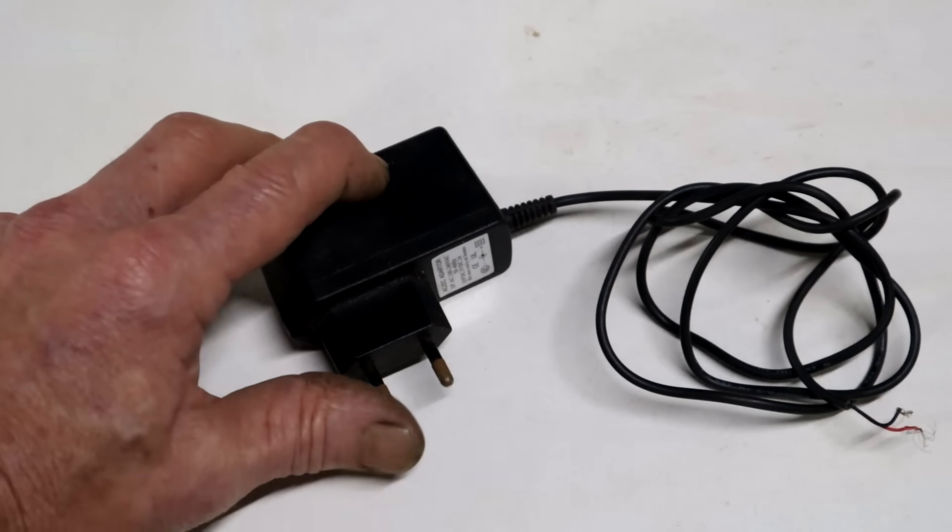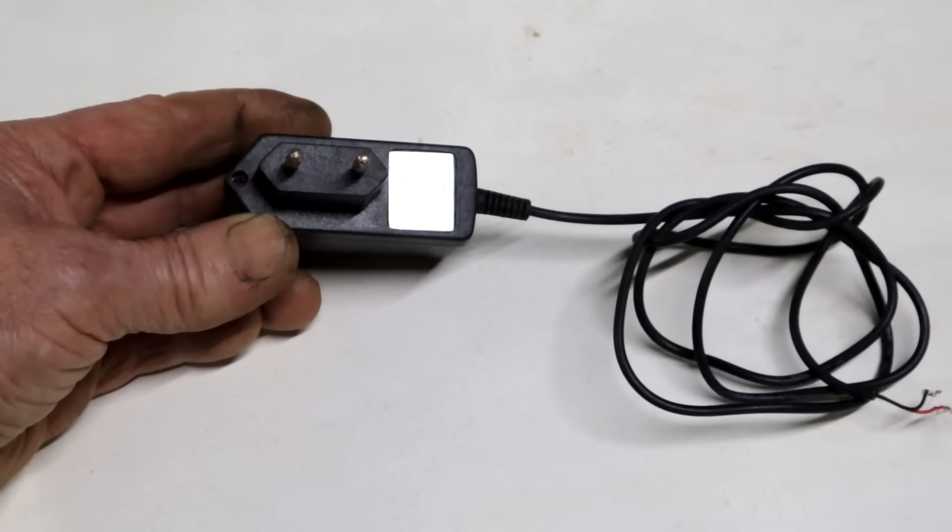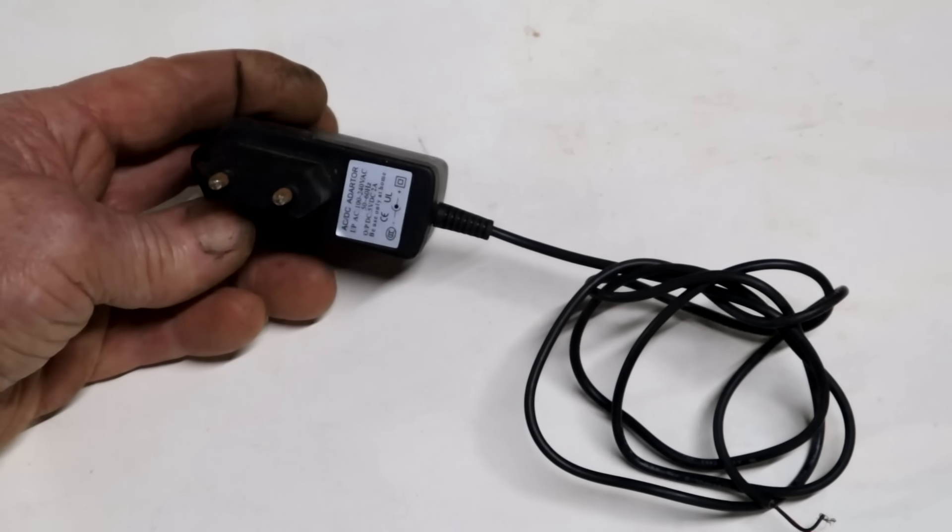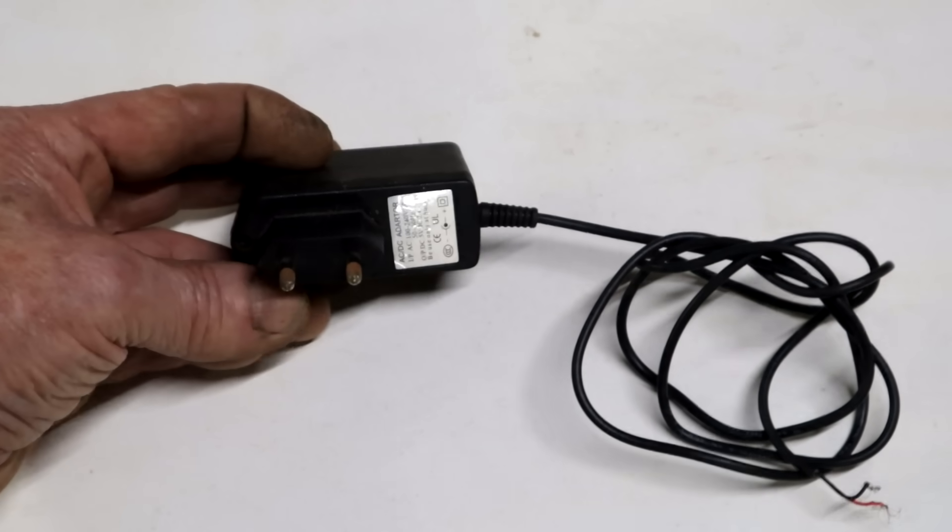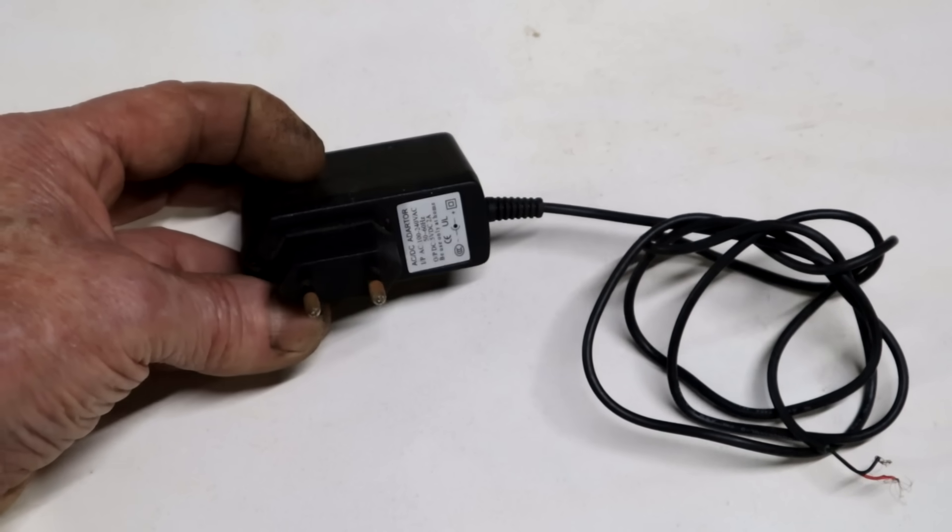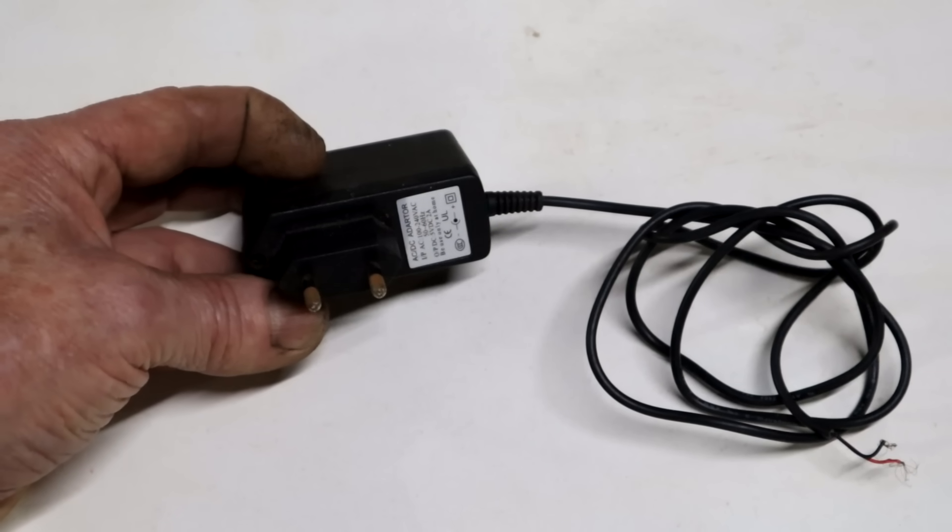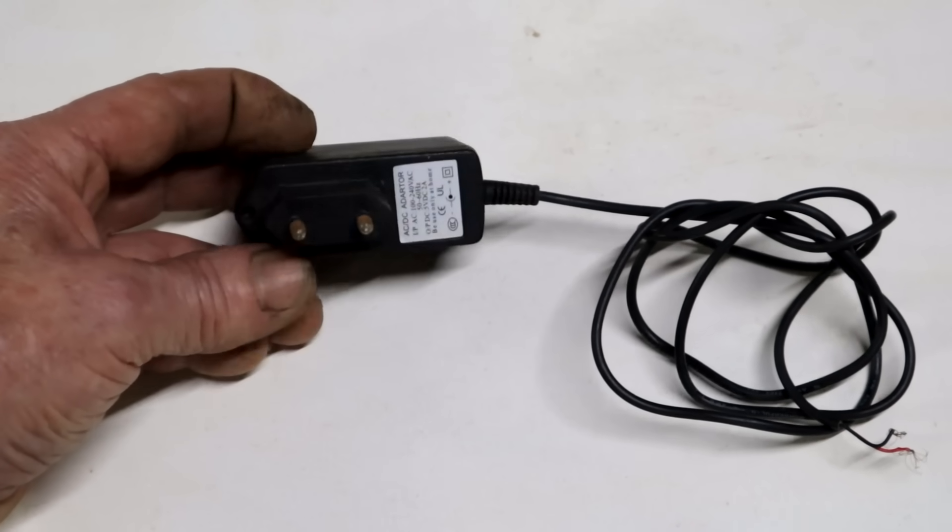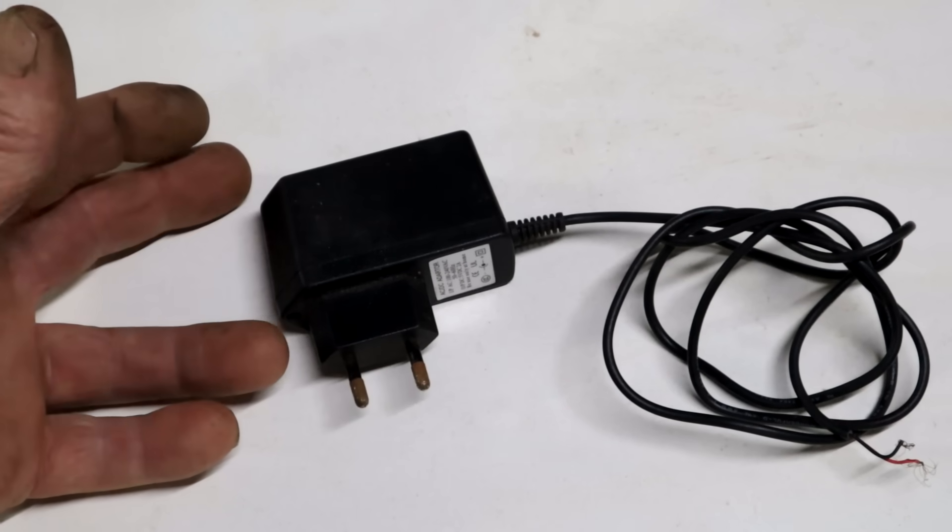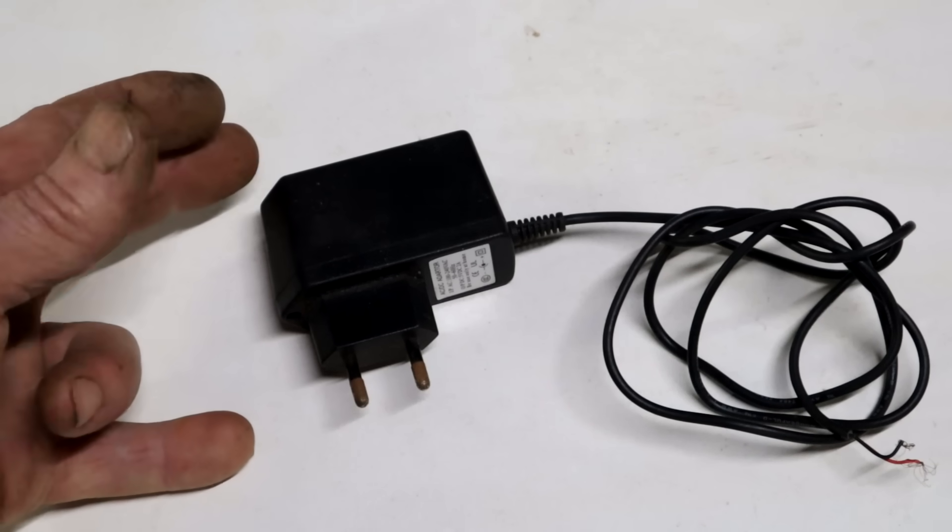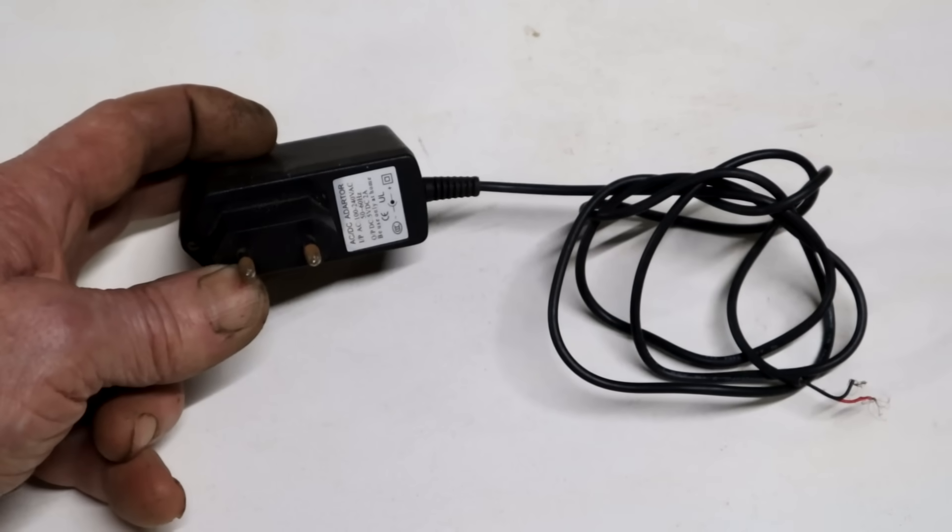You need a direct current power supply. I'm using an old phone charger. This one's got an output of direct current, 5 volt, 2 amps. I think most all of them will work as long as the current output is in the region of at least 1 amp. The voltage is not important. If you have a regulated power supply, more power to you. I don't have one and this has been working for me.